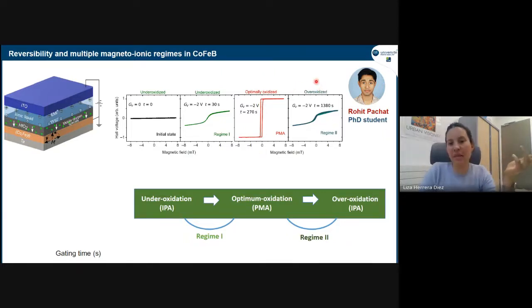So this really resembles the study I showed you at the beginning. If it's too little oxygen, it's in plane. If it's too much, it's in plane. There's a small window where you can get PMA. This is really what we see here, and we see the full range with the gate voltage.